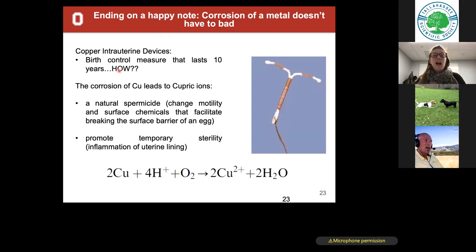Another cool example is copper intrauterine devices. So, right, birth control measures: you can use conventional pills of old, or in more modern times, things like these copper intrauterine devices. There are a lot of people that utilize them these days. And how they're actually working is through corrosion. You can see the copper wire wrapped around this device. This device is then inserted into the uterus, and these copper wires will undergo corrosion in the body. Through corrosion of copper, you get these cupric ions, and these cupric ions are natural spermicides. They basically change the motility and the surface chemicals that facilitate the breaking down of the surface barrier of an egg.